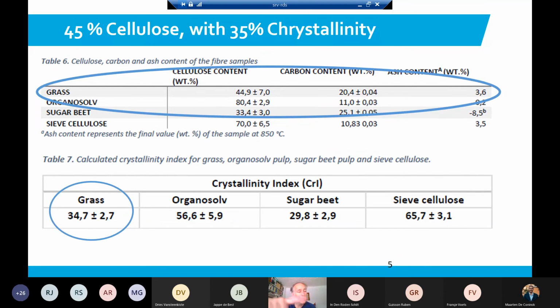So what we did here was we have the same fibers, so the sugar beet and the recycled toilet paper, and we looked at the cellulose content and also at the crystallinity index of this cellulose within the material. So if we look at grass, we can see that roughly 45% of grass is cellulose, so that it's pretty good. It's not the best, but it's pretty good. It's much better, for instance, than sugar beets, but it's lower than recycled toilet paper.